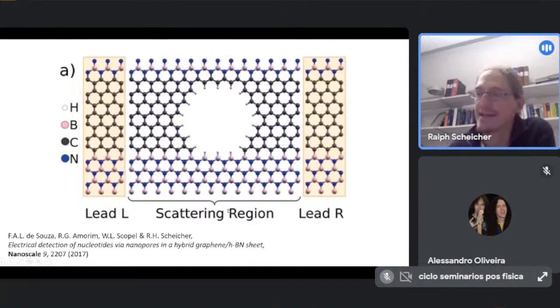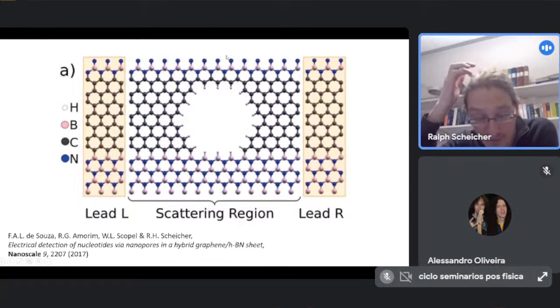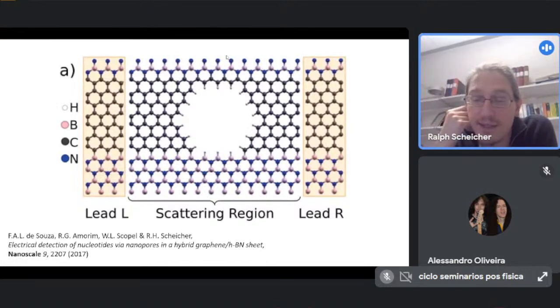Another system, I think the second last system that I want to show to you here today, is one that we came up with, where you have a graphene nanorod, shown here in gray, embedded in hexagonal boron nitride, shown in this purple and blue atomic model here. So to either side you have hexagonal boron nitride, and the interesting thing about hexagonal boron nitride is that it is insulating. It does not conduct electricity very well, and graphene does. So basically the electrical current coming from some left electrode going to the right electrode is constricted first of all to this graphene nanorod.